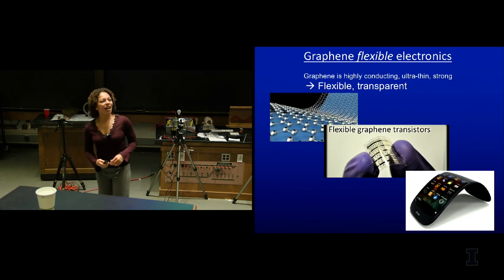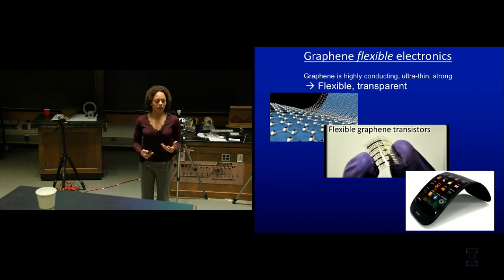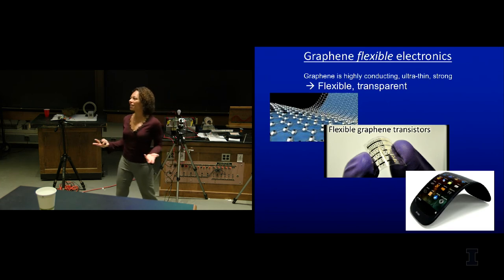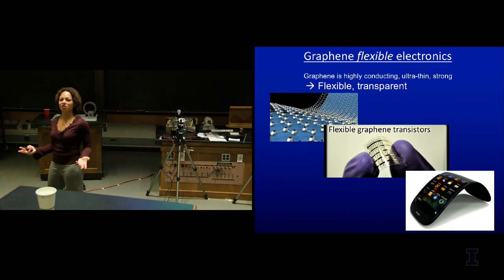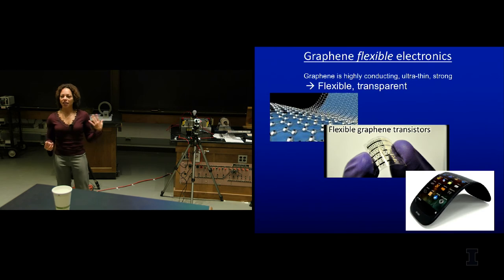Graphene can be heated. You can make it, it's kind of like carbon soot, and so you can heat it to 1,000 degrees, and nothing happens. You make it by growing it at 1,000 degrees, so it's very robust at high temperatures. Now, if you heat it too much, because it's carbon soot, it'll just turn into more soot if you bake it at many, many thousands of degrees. But it's stable up to pretty high temperatures.